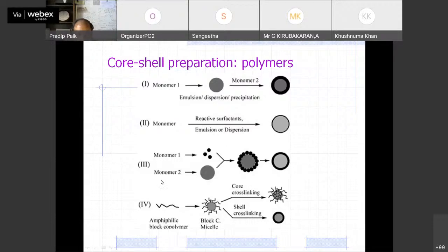So monomer 1 and monomer 2, you see how it is happening. In these cases, monomer 1 was the central part and monomer 2 will be the second part. But in the opposite case, monomer 2 produces the core, then monomer 1 makes small particles. That particle will be deposited here, and further polymerization, layer by layer deposition, will also occur, and a smooth layer will be forming. I will show an example of this.